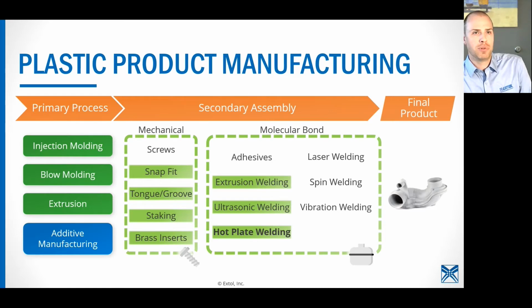What typical gap would you have between the puzzle parts? Great question. About 10 thousandths is a really, really good gap. It depends on the design, the overall constraints, how many degrees of freedom you have in those. The tighter, the better, but you have to be able to get it together. So somewhere in 5 to 10 thousandths is really good.